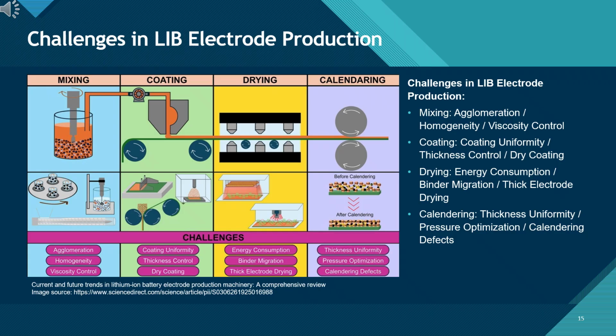During drying, solvent removal requires substantial energy and must be carefully controlled to prevent binder migration or gradients within thick electrodes. Improper drying directly affects adhesion, porosity, and long-term performance.